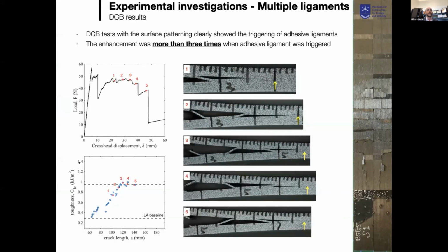And this is something that in terms of properties, if you look at the effective properties now, your P delta curve now is going to look something like this. And you can see that the toughness, the one that you measure from a macroscopic point of view, is multiplied by 3 or 4.